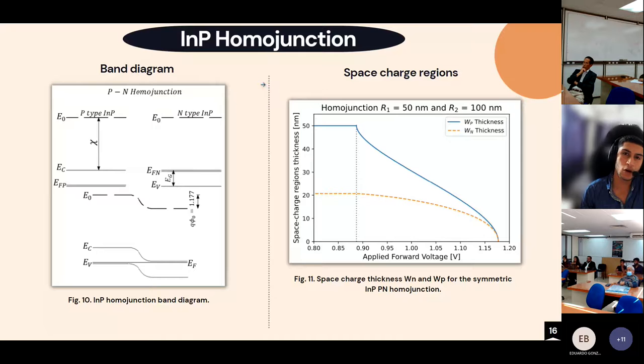For the indium phosphide homojunctions, on the left side, we can see the band diagram when the built-in potential is equal to 1.177 volts. Like in the heterojunctions case, the space charge region thickness can be obtained by using this built-in potential. So on the right side, we have the space charge thicknesses omega n and omega p for the symmetric indium phosphide homojunction.